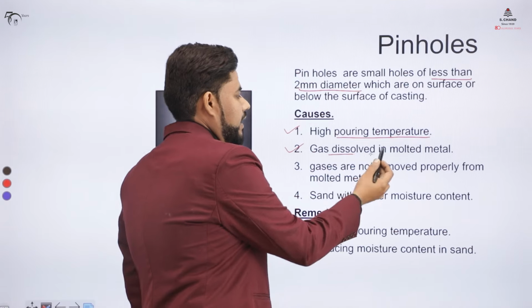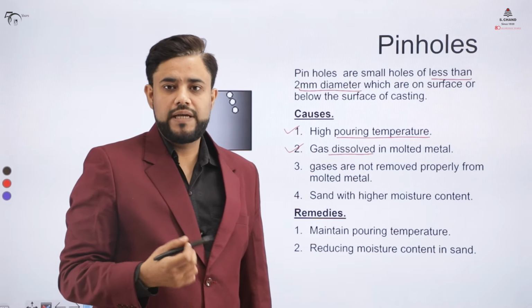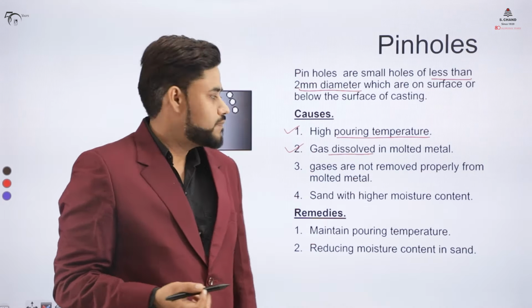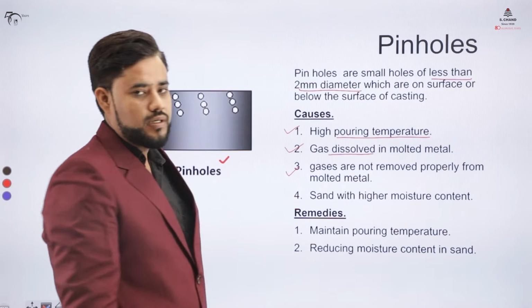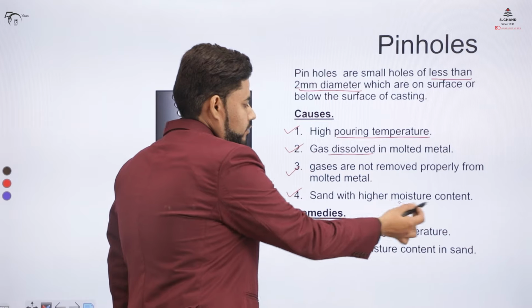And because of the gas that is produced during the reaction, and that gas is incorporated or dissolved inside that molten metal, this pinhole is being created, and gases are not properly removed. Because of that, the hole is created. The sand may contain moisture.